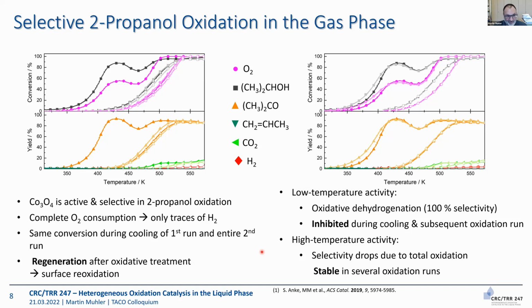Okay, now we start the first heating experiment. We heat up in 2-propanol and oxygen. We monitor conversion, and you see we convert 2-propanol, then conversion decreases, and then we go up to full conversion. Oxygen is consumed as well, so oxidative dehydrogenation seems to go on. And when you look at your mass spectra, then you see immediately and are happy that it's exclusively acetone that is formed.